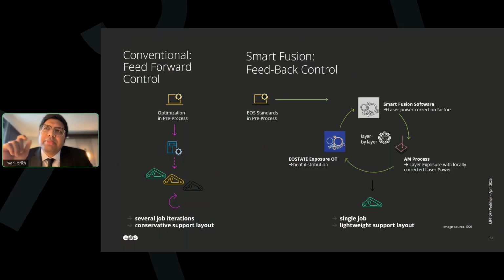based on the value that the user enters at the start of the job. Like I would say 3% variation from the nominal process parameter of 340 watts, for example. Then it would reduce laser power up to 3% of 340. And you don't put some arbitrary number so that you get a keyhole porous part. So it gets to that correction factor based on looking at the gray value variation, and it reduces its laser power. It does it on a particular part, not the entire layer. So you'll see that in a minute. The next video shows a different material, Inconel 718. Go to the next one.